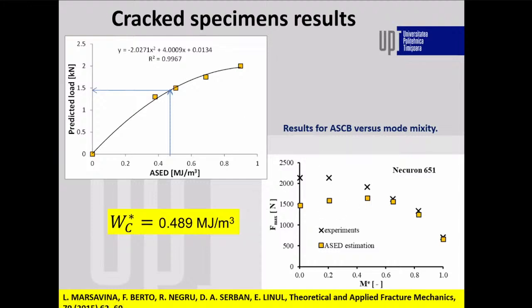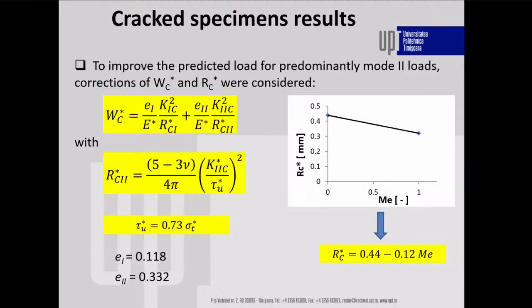So what we were thinking there to try to change the control radius in order to improve these predictions. This is what we did. So we calculate the control radius for mode 2. We use the fracture toughness results determined on compact shear, and we use ultimate shear stress, which was a proportion from the ultimate tensile stress, and we found a linear relationship for the control radius relative to the mode mixity.